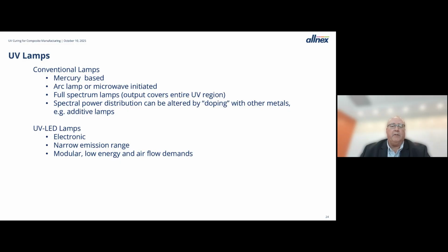More recently, there have been UV LED lamps that people have created. And I've got to give credit to the lamp manufacturers. They've increased the power and improved the efficiency of lamps quite a bit over the last few years. The big difference is that these lamps are electronic and have a very narrow emission range, whereas the mercury-based lamps put out energy across the spectrum. UV LED puts out energy in a very specific band in the UV. So you've got to be very judicious in which photoinitiator you select to use with UV LED lamps.